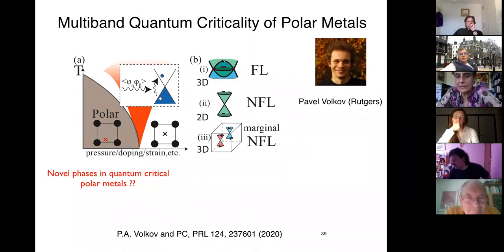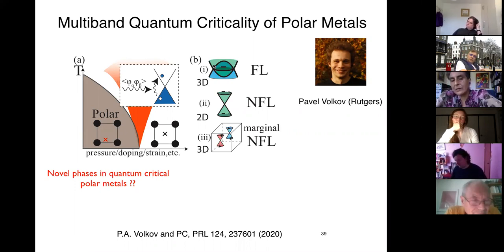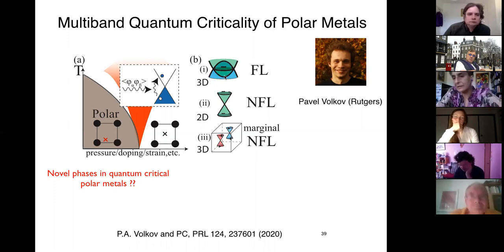Yeah, so actually thank you for the question. And of course, I didn't get much time to tell you about it. This is a very strange Fermi liquid because the system has, for example, the critical boson has a sound velocity that's closer to the Fermi velocity. The point is that it has anisotropy and it has some very strange dispersive behaviors, but it doesn't have the instabilities that these other two do. That's what we found. And we made some predictions for experiment based on some of those anisotropies. So in each case, there's very strong renormalization of the critical boson. So when I say Fermi liquid, that doesn't mean it's not interesting. It's just not non-Fermi liquid, but there's some very interesting properties to this.